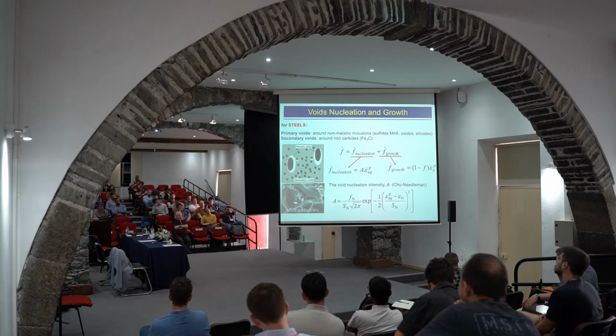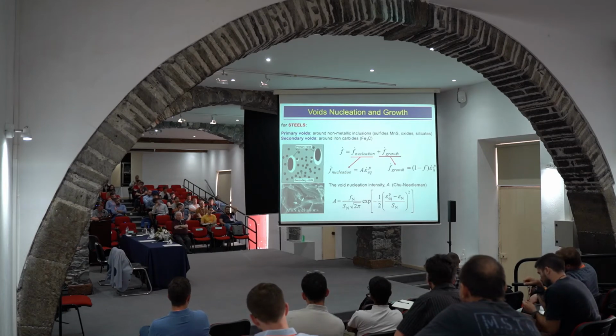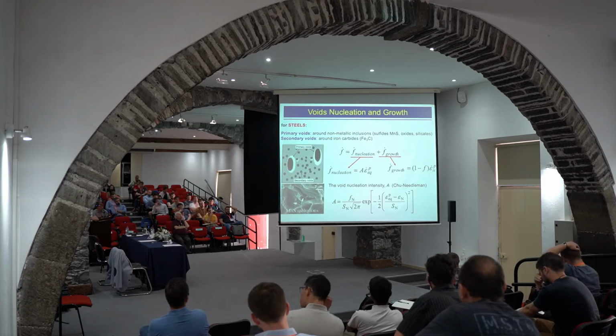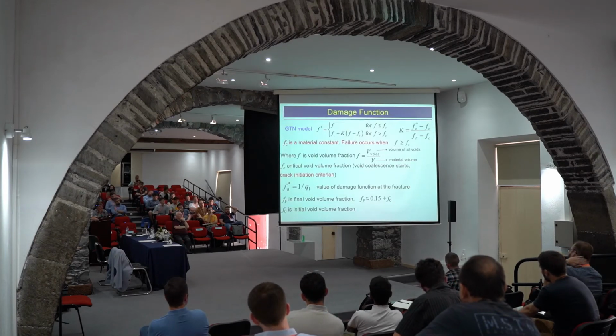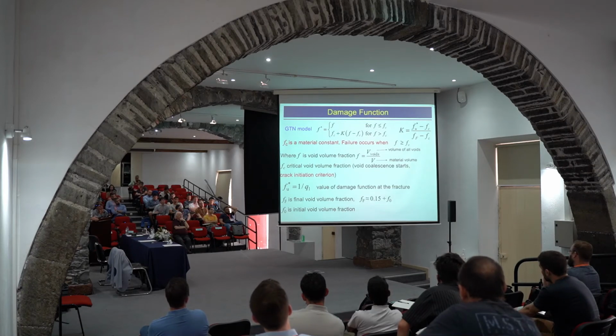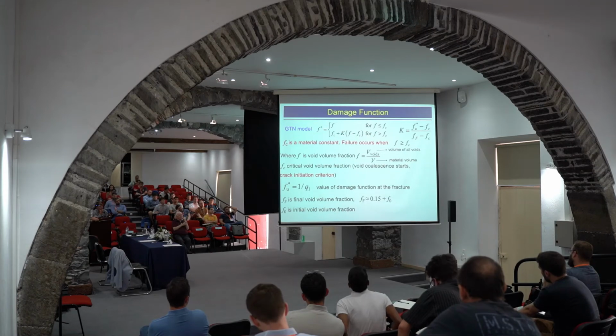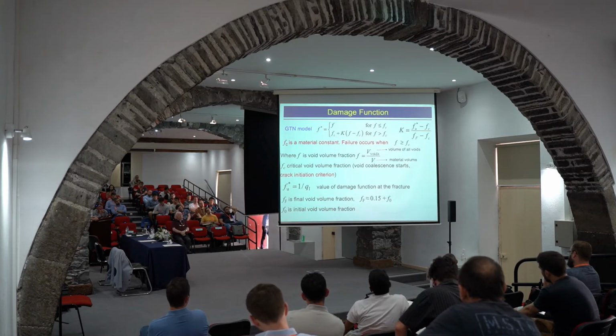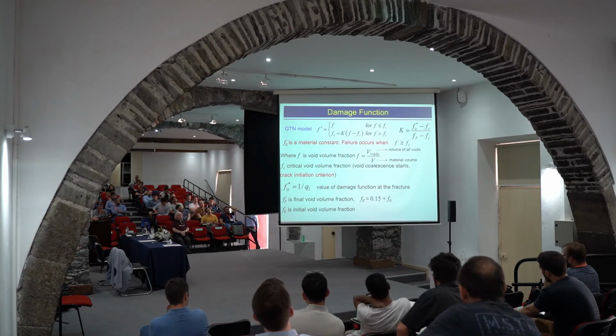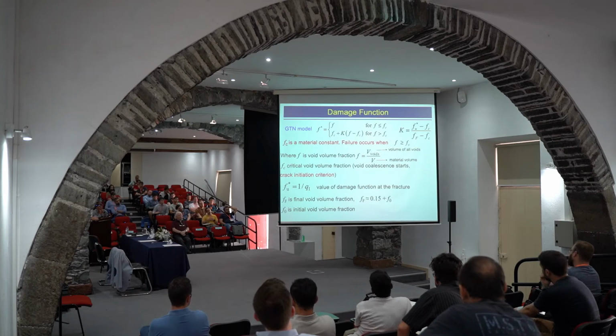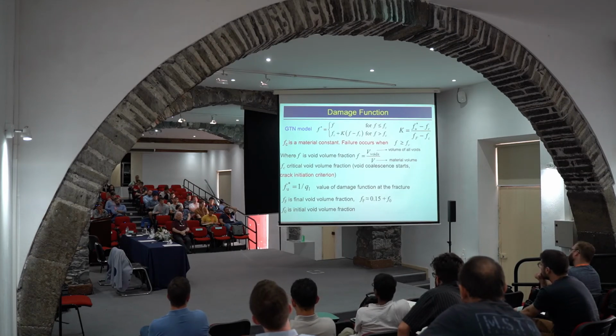I'm emphasizing this because they are a bit different, and in some cases these secondary voids can be neglected, but not in the case of steel, with at least a couple of hundredths of a percent of carbon, which is big, or better to say, not negligible. This so-called Gurson-Tvergaard-Needleman GTN model is a bit more complicated than the original Gurson model because it doesn't take into account just F as a void fraction, but also it distinguishes two values, one before getting a critical value and the other after getting it. It is something like a stress strain curve, so linear elasticity before we get to yield strength and then afterwards different behavior.